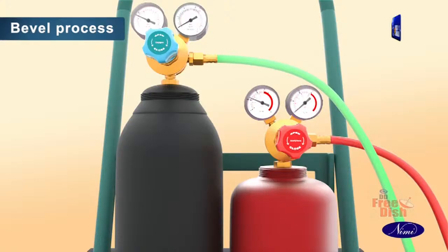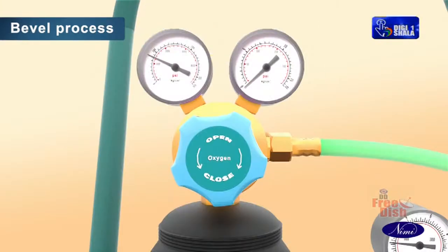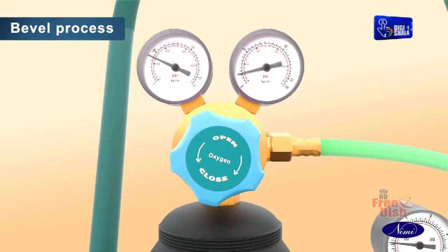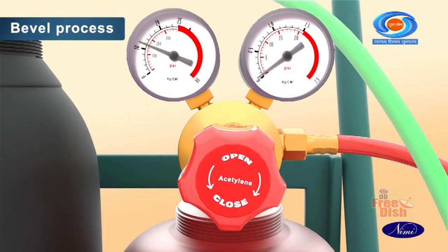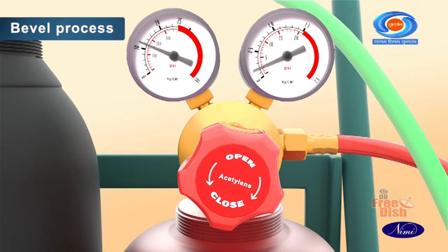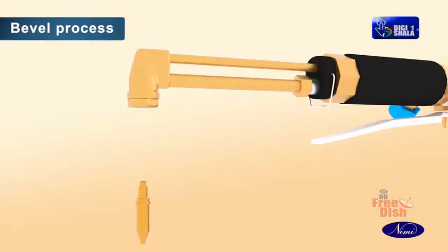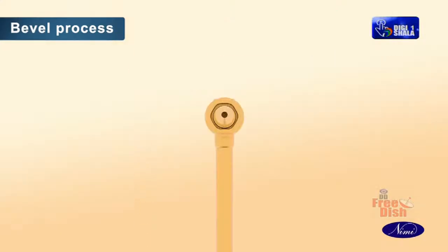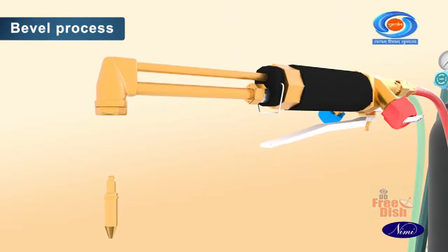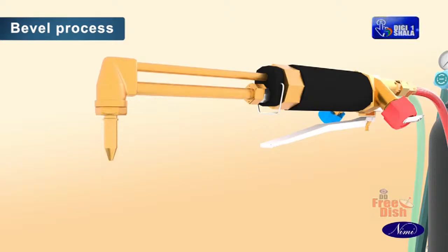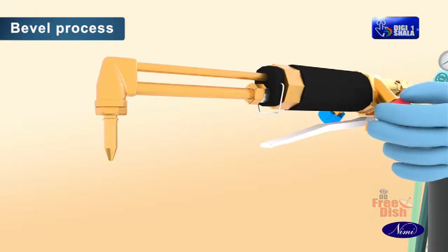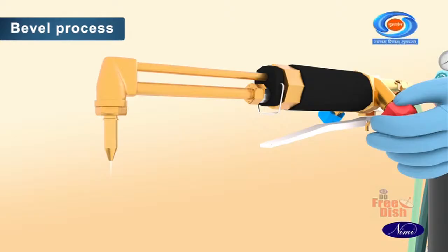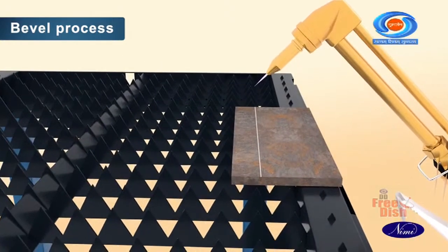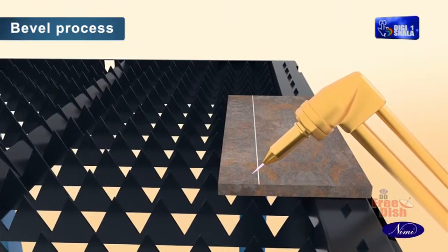Set the gas pressure to 1.6 kg per square centimeter for oxygen and 0.15 kg per square centimeter for acetylene. Fit the correct cutting nozzle of 1.2 mm dia orifice cutting nozzle. Set the cutting nozzle in the blowpipe and adjust the neutral flame for preheating, and hold the cutting blowpipe nozzle at a 45-degree bevel angle.